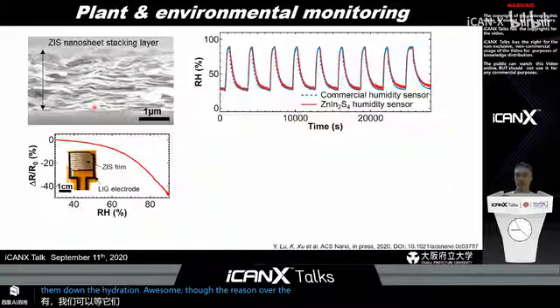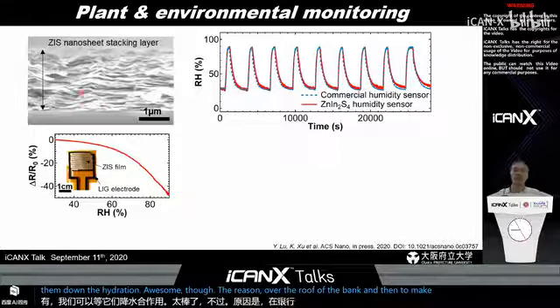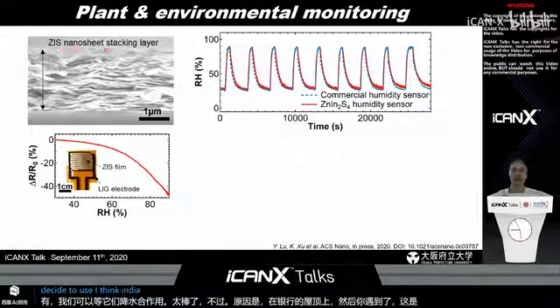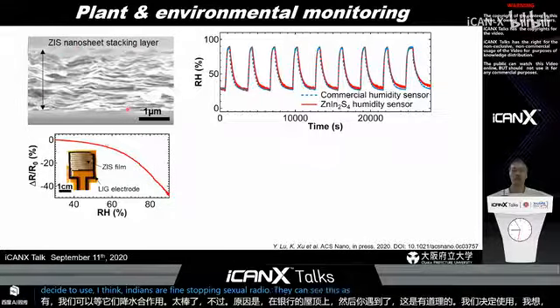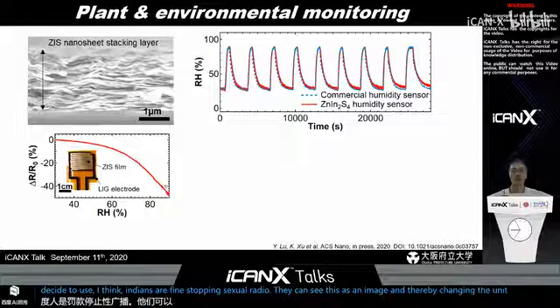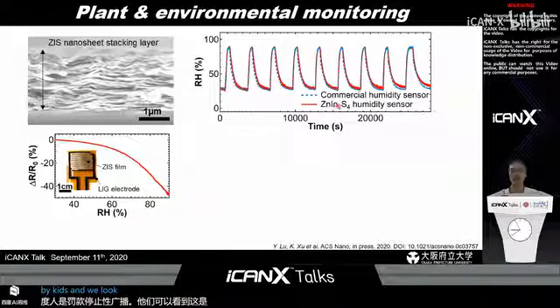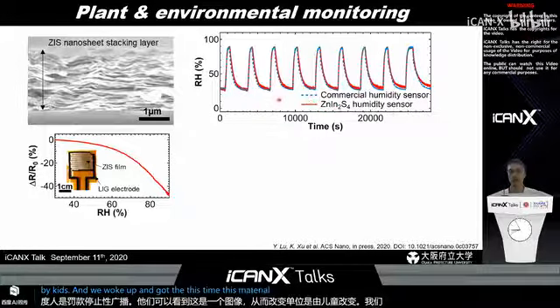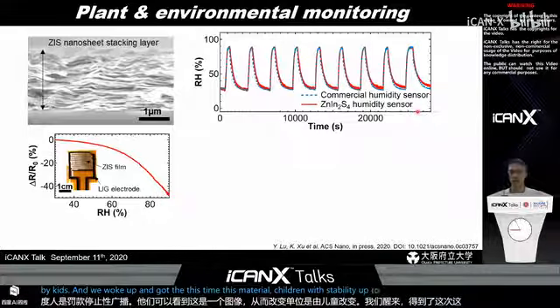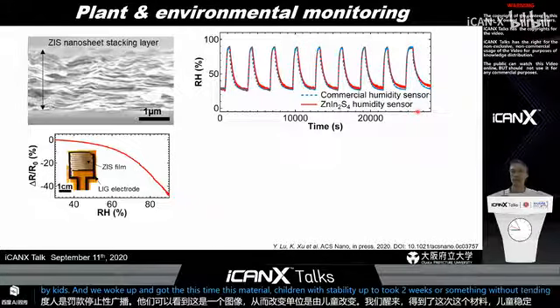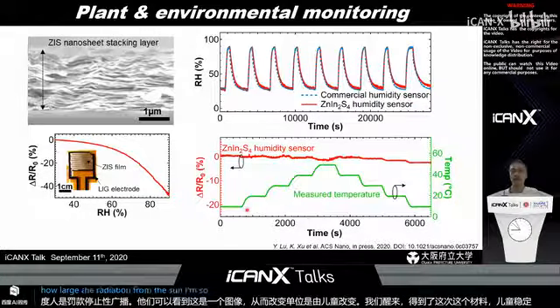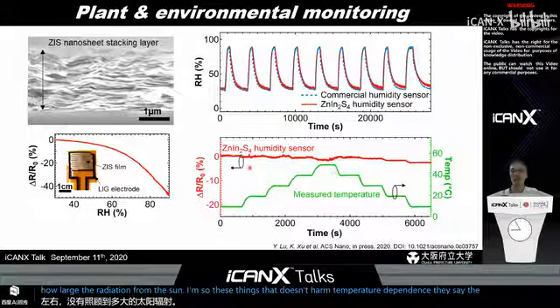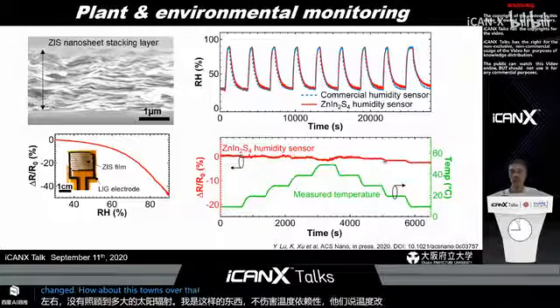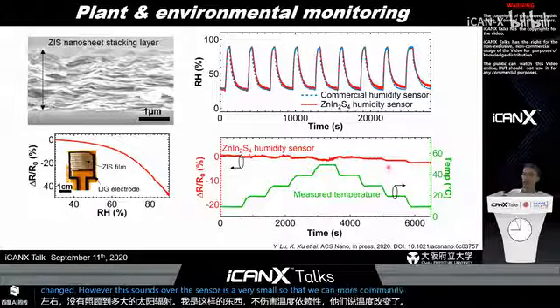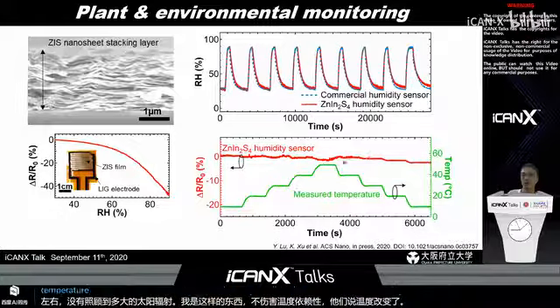leaf of the plant. To make the humidity sensor, we decided to use the zinc indium sulfide nanosheet stacking layer, as you can see in this SEM image. By changing the humidity, the resistance changes like this. We also confirmed that this material showed good stability up to 2 weeks without large degradation. And this sensor doesn't have a temperature dependence. This is a temperature change. The resistance of the humidity sensor is very small, so we can monitor the humidity individually, even under the temperature condition change.